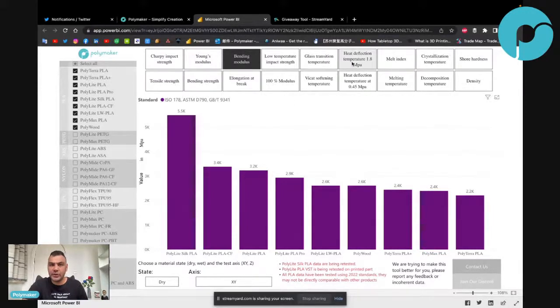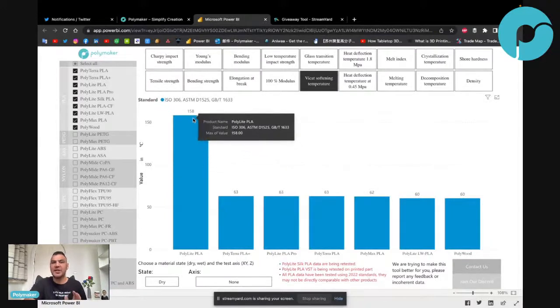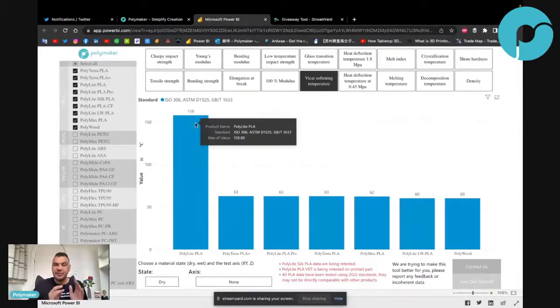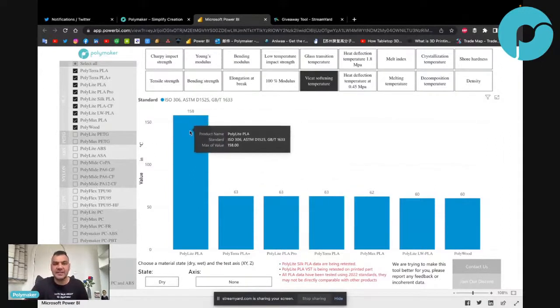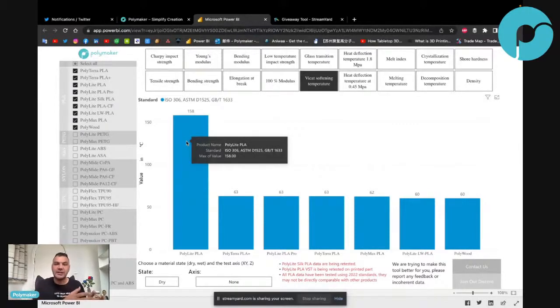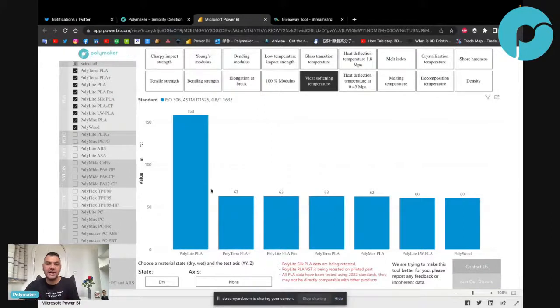Polylite PLA VST is the same. If you go to the Vicat softening temperature, you can see Polylite PLA is 158. The reason is that Polylite PLA is an old product. Before, we were taking the Vicat softening temperature of the filament, not the printed part. Because of our jam-free technology, the filament has a high heat resistance, but once it's processed, the heat resistance of the part is the same as regular PLA. So we need to retest this Vicat softening temperature, testing the printed part, not the filament. And all the new PLA data are using the 2022 methodology, and all the other materials are using the old methodology. That's why sometimes comparing our PLA with other materials can be a little bit strange.